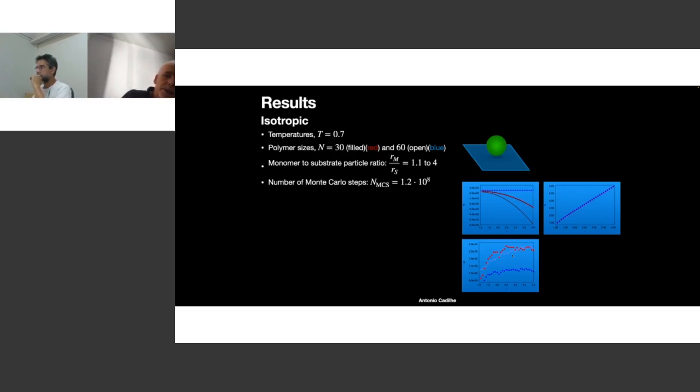Now there is also here another third curve, a lighter one, that is the simulations on the flat, smooth substrate. And these ones show that the influence of the crystalline surface or substrate is determinant in the dependence of the diffusion coefficient with gamma, in the sense that is this ratio I pointed out before.